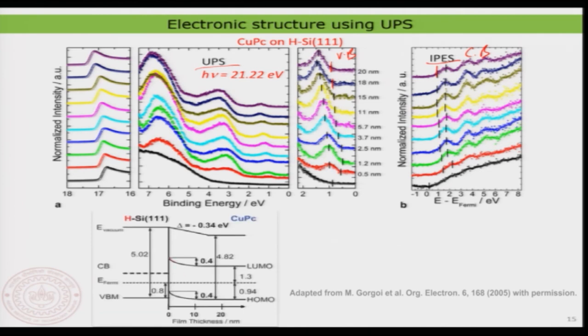So that means the LUMO and the HOMO of the molecule with respect to the surface density of states is changing as we move away from the interface. So this represents the film thickness. This is the interface, and as the thickness of the film increases, you can clearly see that the molecular HOMO and LUMO are changing with respect to the conduction band and valence band of the surface. That is something I've already told you. This is something that we would expect, and now we can also clearly measure it experimentally if we combine UPS and IPES, the inverse photoelectron spectroscopy. So together you see clearly that we have a greater understanding of the interfaces.